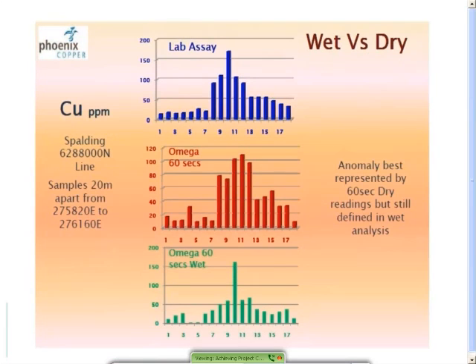Phoenix even did some work to understand the effect of moisture on XRF results. Portable XRF's generally okay on samples up to 10% moisture. The presence of water within a sample will diffract X-rays emitted from the analyzer and not allow all of those fluorescent X-rays from the sample to return to the XRF's detector.